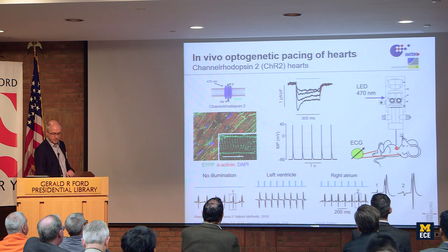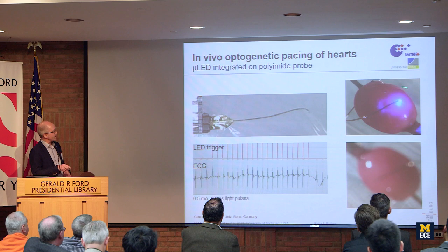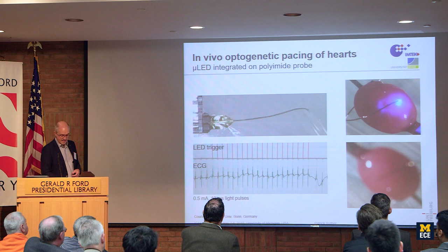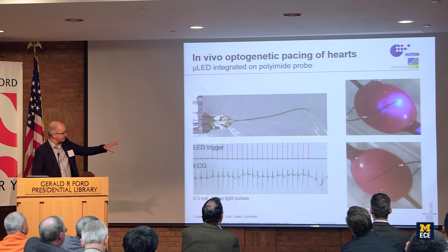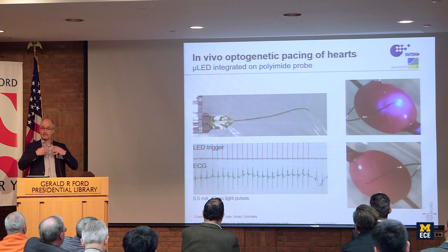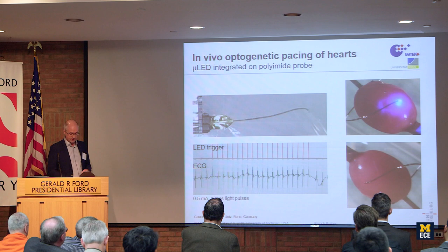Now, in our case, we tried to use our LEDs on a flexible substrate. You have seen the 2D arrays, so we placed it directly onto the heart, and we have a Langendorff perfused heart freely beating then in a solution. It's not clearly seen, but the heart is beating, and at least with the ECG signals, we can clearly show that pacing can be done with a single LED positioned on the heart itself.